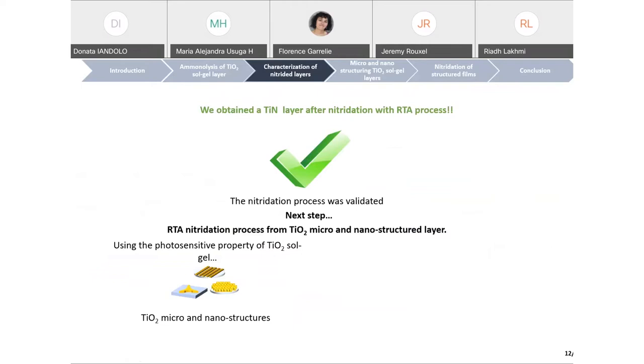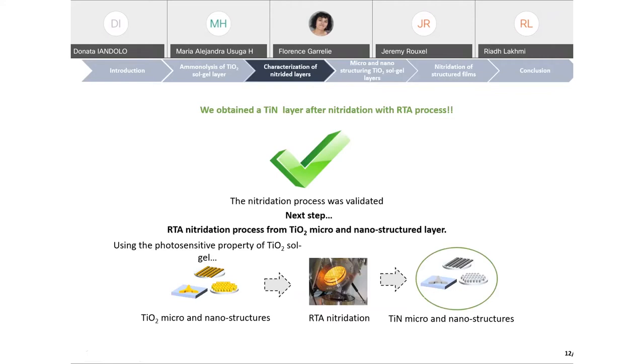So we obtain a titanium nitride layer after the nitridation process with the RTA process. So we can say that the nitridation process was validated. The next step is the RTA nitridation process from the titanium dioxide micro nanostructure layer, using the photosensitive property of titanium dioxide sol-gel. When we realize the RTA nitridation on the micro nanostructures, we want to obtain titanium nitride micro nanostructures.